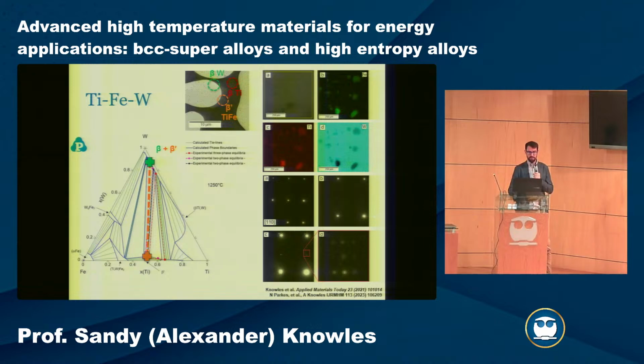With this alloy, you have the BCC tungsten, you have BCC titanium, and then you also have this beta prime titanium iron. So there is this equilibrium between these different compounds within the phase diagram. When we zoom in with TEM, if we go into these dendrite regions, the tungsten-rich regions, we see a secondary phase within them. We were curious whether that phase might be titanium iron. This is transmission electron microscopy again, where we're looking at the composition of those precipitates. We see that they are enriched in titanium and iron, with the matrix being tungsten. Then we can do selected area diffraction, where we go into the TEM and do electron diffraction, and we can see characteristic reflections of this beta prime intermetallic. So we have something that's rich in titanium and iron, but it also has crystallography that's consistent with the titanium iron phase.